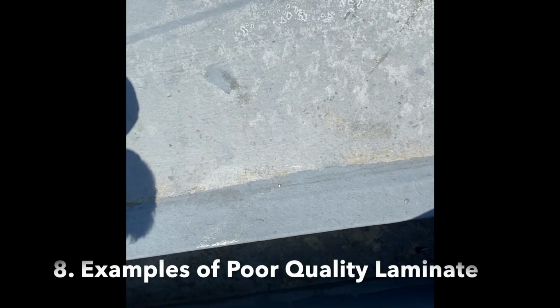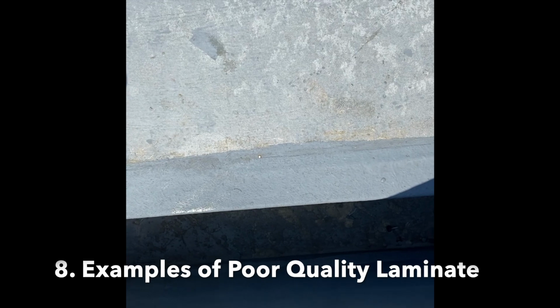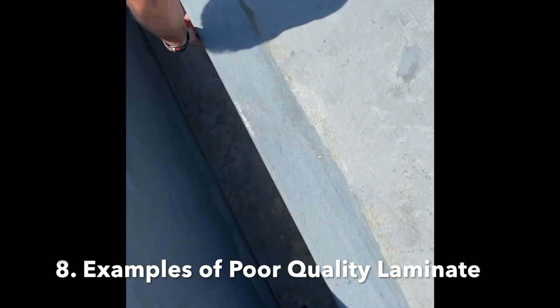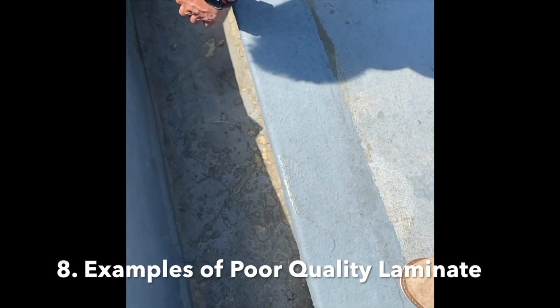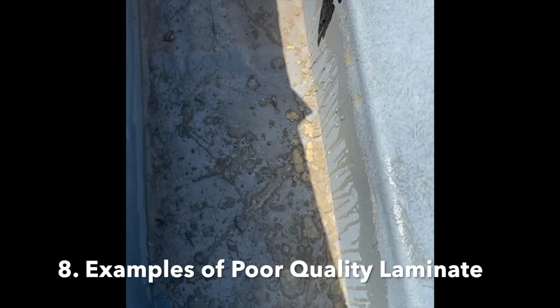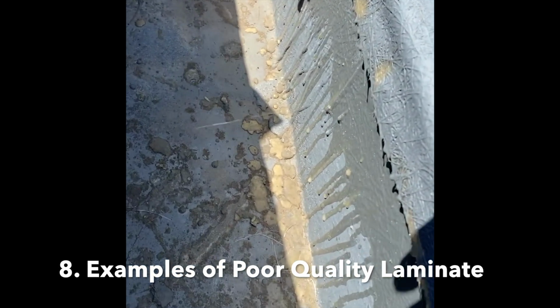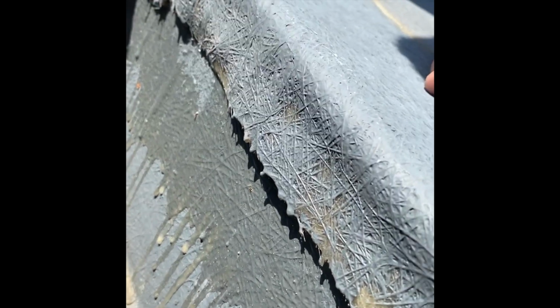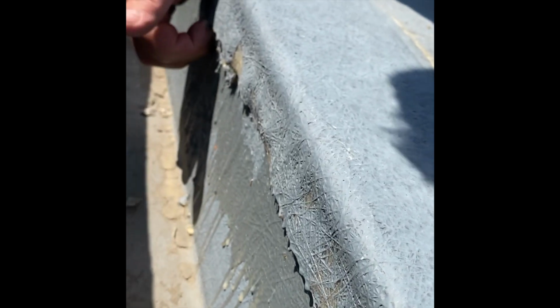This section intends to show what can go wrong with a fiberglass laminate. Whilst these examples show the final top coat after it's been applied, it's also important to note the condition of the underlying laminate. This example shows inadequate resin coverage, an absence of a seamless barrier between the different sections of glass fiber matting, usually indicating no paddle roller and incomplete resin application. It's no wonder this roof was leaking through the ceiling in this area.